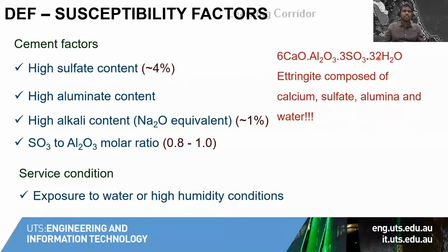So one thing which is not in this formula is alkalis, but that can also contribute to delayed ettringite formation. How? We saw earlier, the higher the alkalis in the cement, the more the chance of decomposition of ettringite or dissolution of sulfates will increase. So alkali content is also very important. And then we saw 3 examples. All 3 examples are associated with moisture exposure as well.